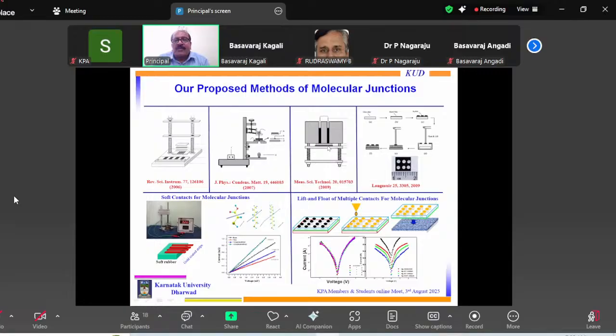Another way of making a molecular junction is by taking a mercury column. This is a multiple contact. In fact, you can lift the contact and float it on the surface because we cannot do thermal evaporation. If you do thermal evaporation of the top contact, it will go and damage the monolayer. Therefore, you cannot have the response of the molecule.